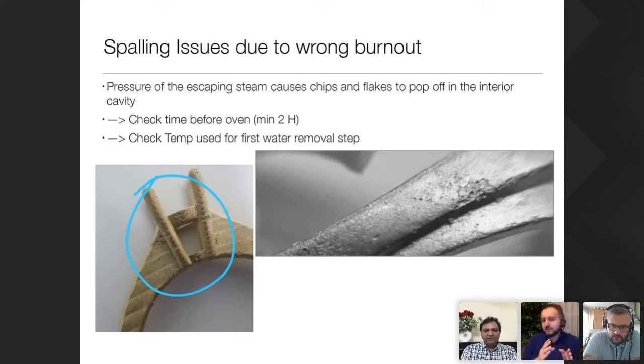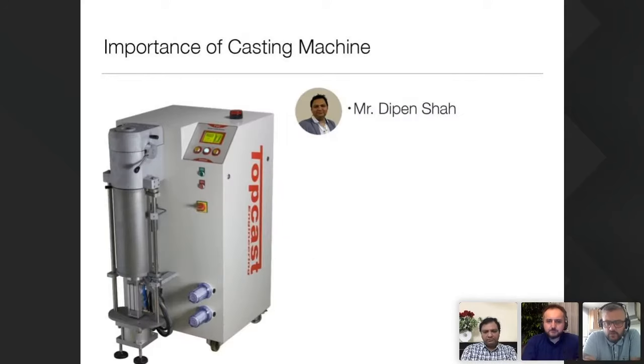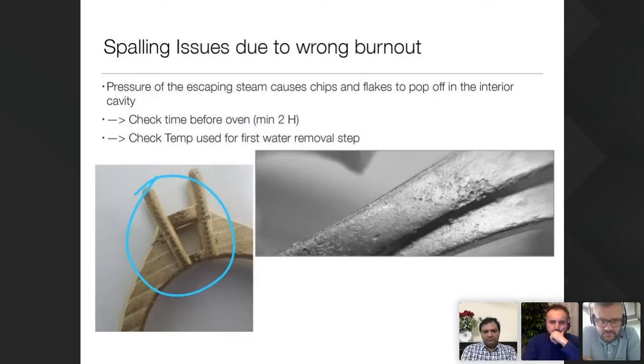But as I mentioned earlier, the processes for resin and wax are different. So you need to consider the steps, and you need to consider the speed that's happening. So in our resin, we don't see a lot of those issues. If you follow the instructions properly, you will not see this happening. But go back, that issue does happen with wax also.